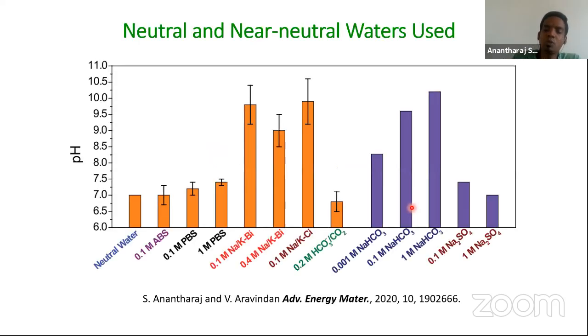the electrolytes first, because I have told that when you do water electrolysis in extreme pH solution, we have very easy options. For pH 0, you go with 0.5 molar H2SO4 or 1 molar HCl. For highly alkaline solution, you go 1 molar KOH or NaOH. Very simple. So you don't have any confusion there about the electrolytes. But when it comes to neutral and near neutral water splitting, we have a variety of choices, and that has to be made depending on your utmost end application. I mean, where you want to use your electrocatalyst eventually, and the place and the requirement.